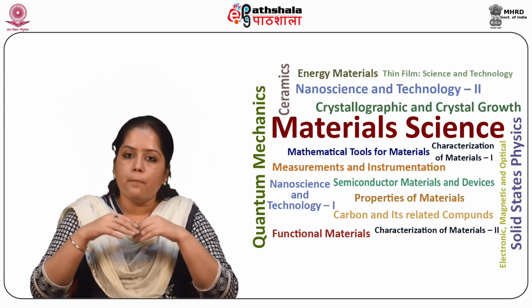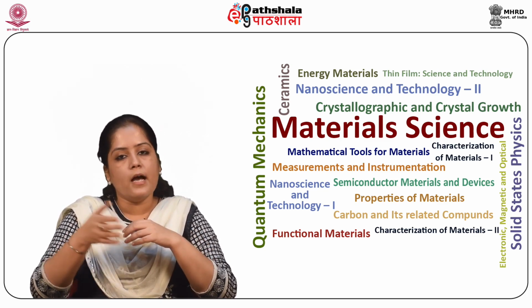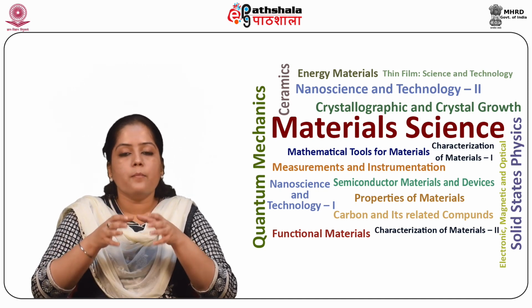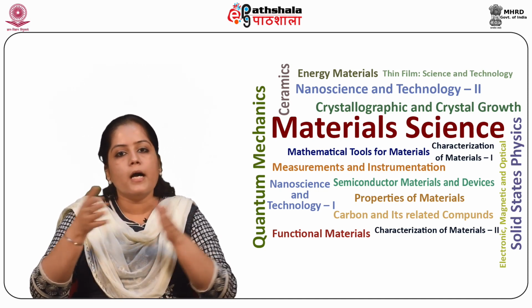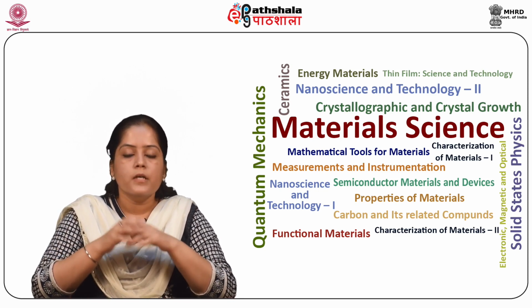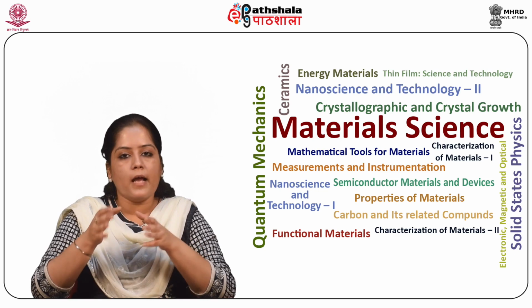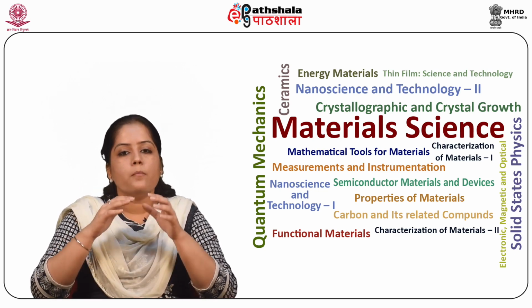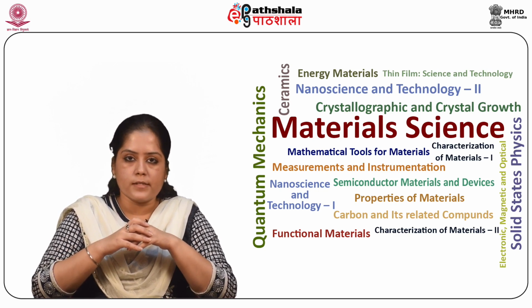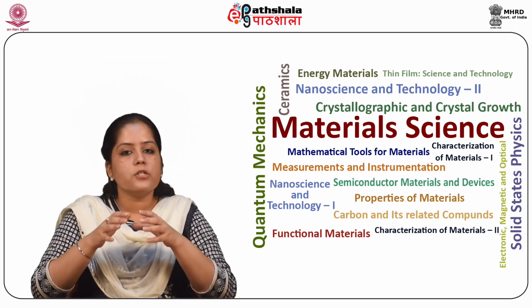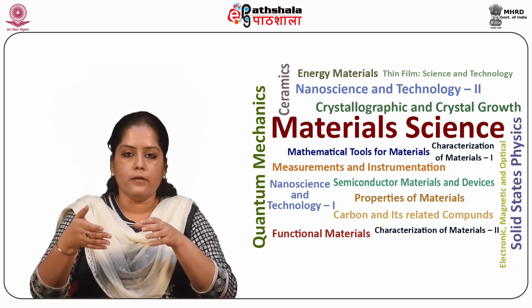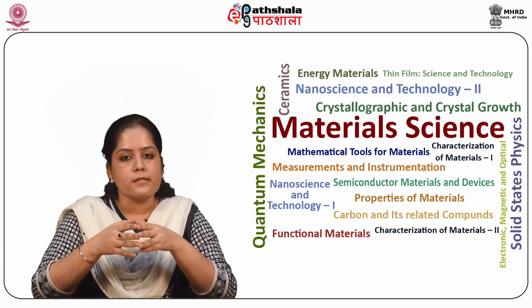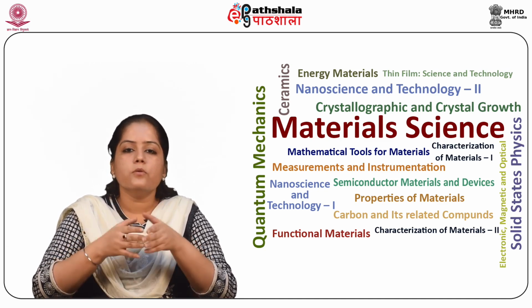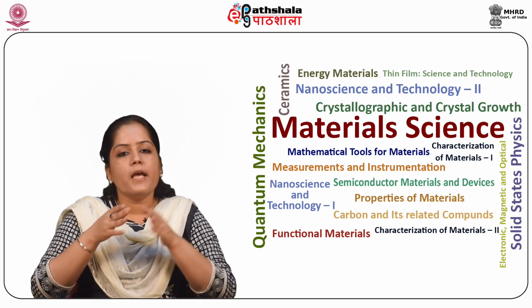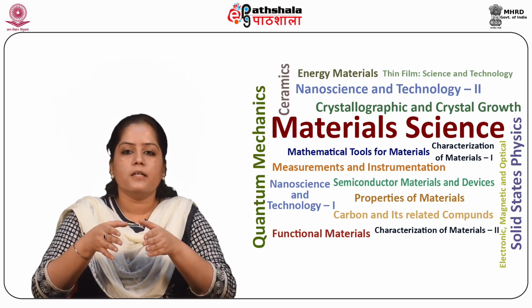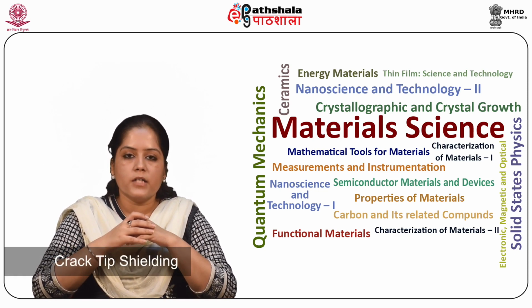The metals have much higher fracture toughness than ceramics. So there is a plastically deformed zone ahead of the crack tip. The stress experienced by the crack tip is reduced, so much less than the applied stress. In this effect, the measured fracture toughness is higher. The reduction in the stresses at the crack tip due to the plastic deformation or any other process occurring near the crack tip is called crack tip shielding.